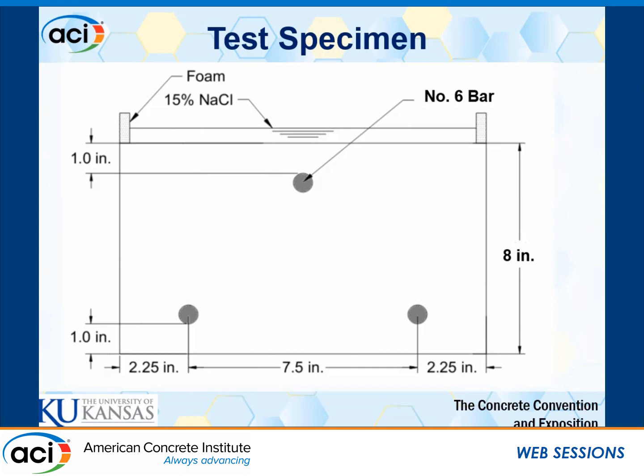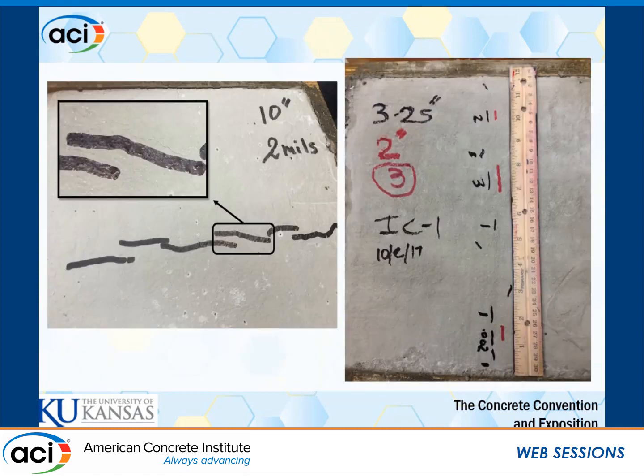It's pretty easy to turn this into a corrosion test specimen. All we really needed to do was provide a bottom mat of steel to serve as our cathode, and then we attached a foam dam around the edge of the top there to hold our salt solution on top. And we use a 15% salt solution with our test program. Here's an example of the end product from the settlement cracking test. So after that concrete sets in 24 hours after casting, we measure both the length and the width of those cracks.